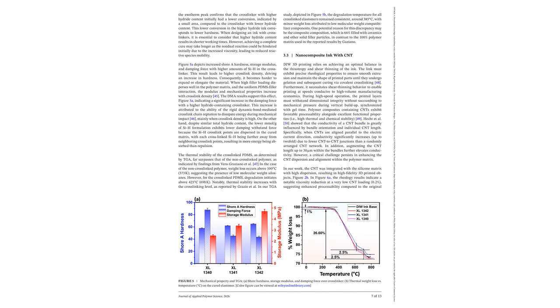The authors also examined thermal stability using thermogravimetric analysis, or TGA. They found that all the cross-linked silicone elastomers were very stable, with degradation only beginning around 385 degrees Celsius. This is a significant improvement over non-cross-linked PDMS, which can start to degrade at much lower temperatures.